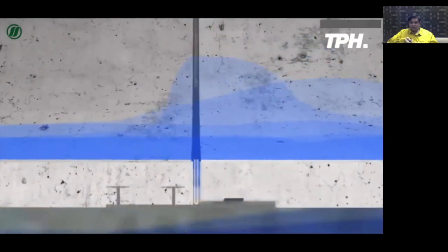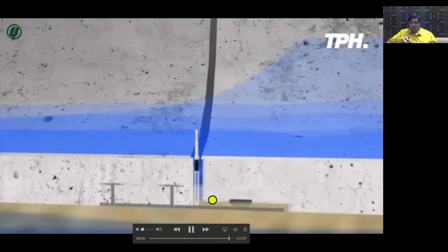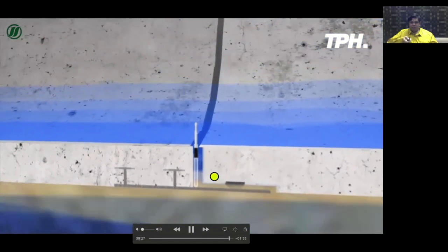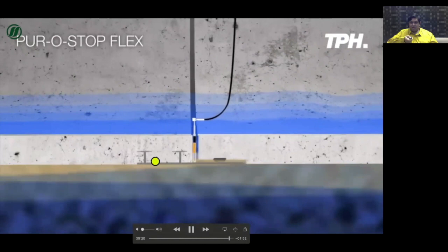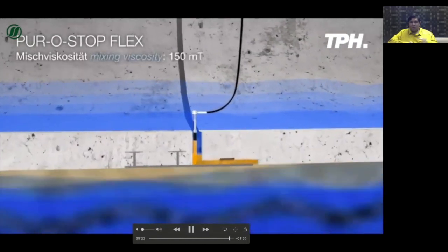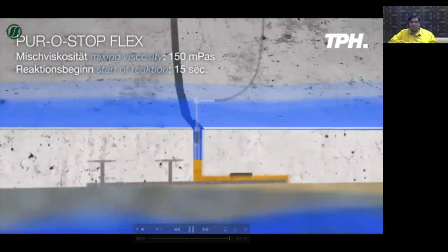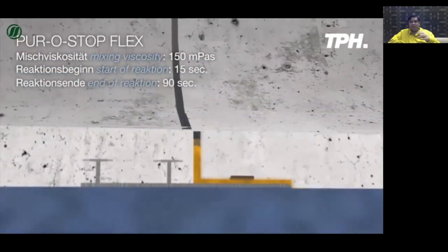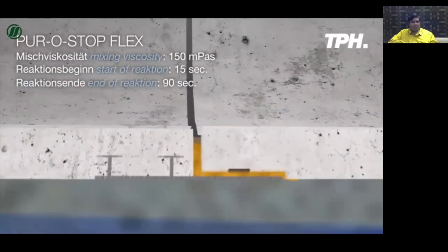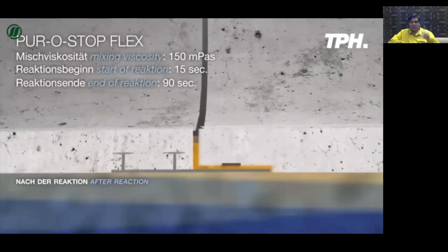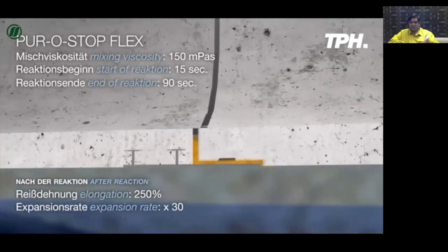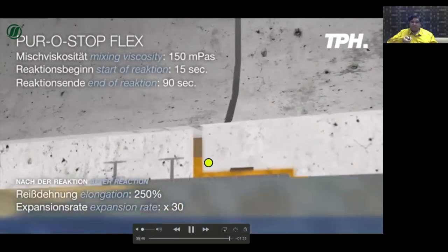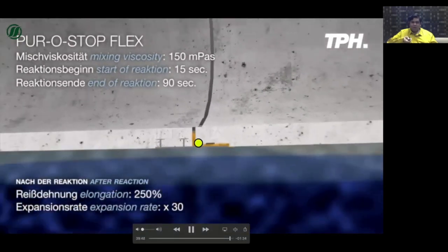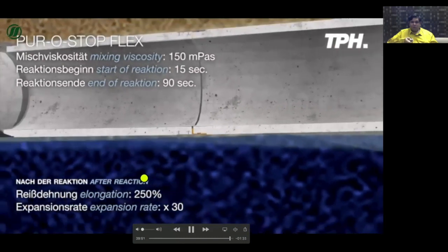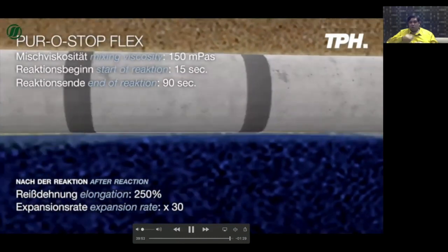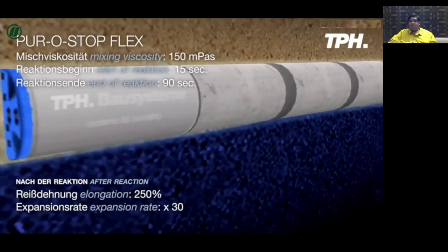So simply drill in through the seal. Okay, you start your injection process, and it solidifies and holds together like Purostop Flex. This is one of the very ductile kind of polyurethanes. Very low in viscosity, reacts in hardly 15 seconds, and the reaction is complete within 90 seconds. It can be used very easily in flowing water as well. Good extension. So overall, it can seal these kind of applications very, very quickly.